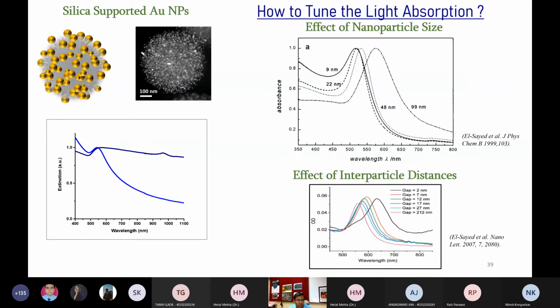So what we wanted to do is make a material which absorbs the entire visible spectrum. In general, if you take a gold nanoparticle, the absorption spectrum is this blue line. It absorbs around say 560 nanometer and a very weak absorption at other wavelengths. What we wanted is this dark blue line, a broadband light absorption, which absorbs all visible and even near IR. So that means I'm able to harvest a large amount of solar energy, which I can use for catalytic application.